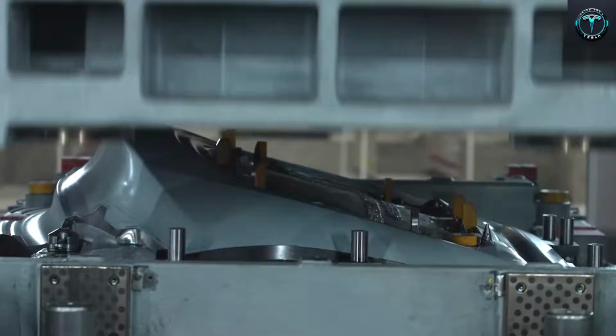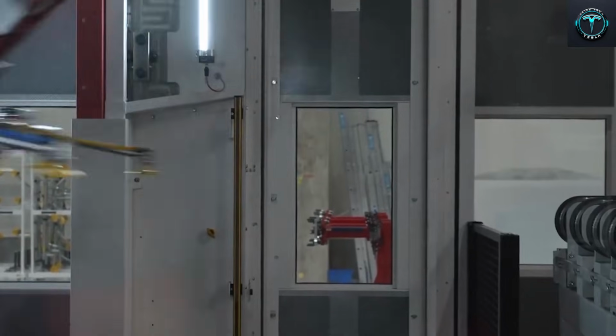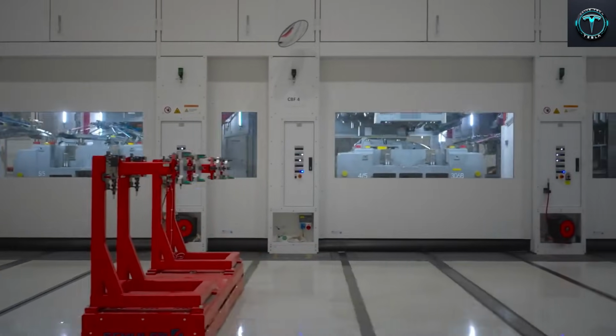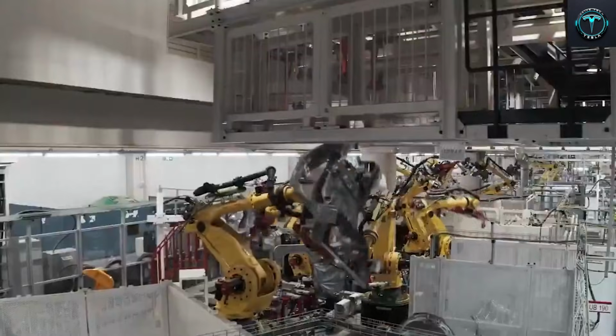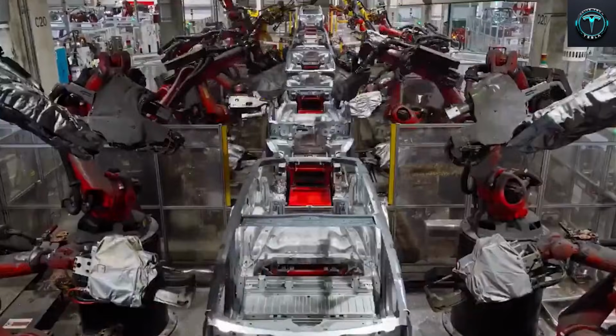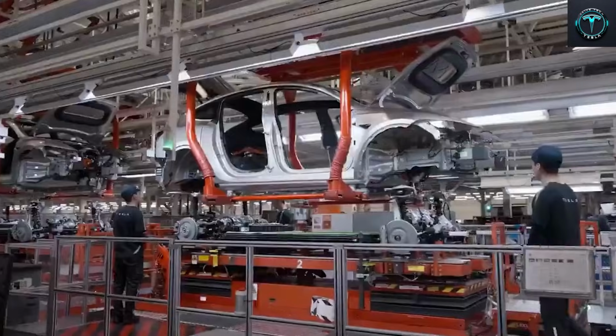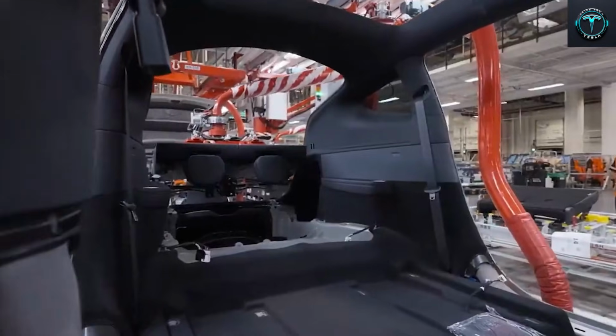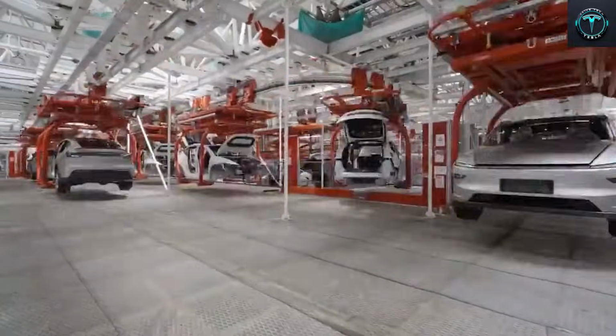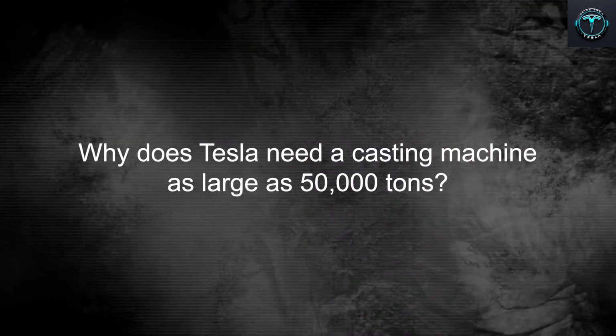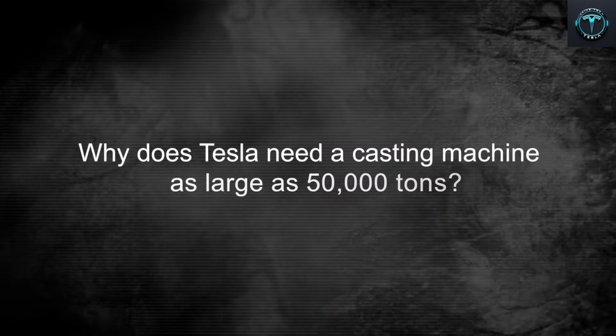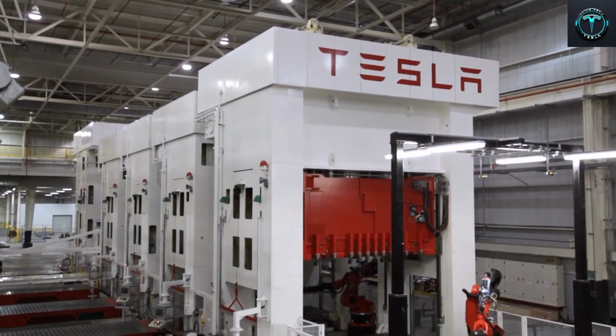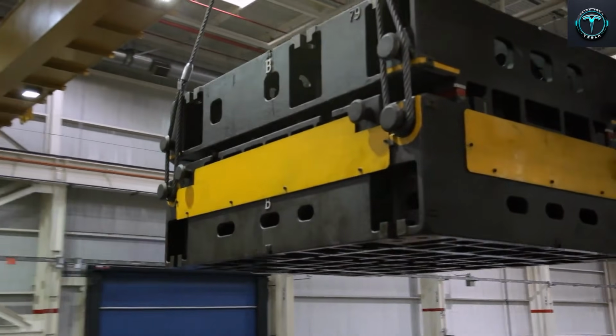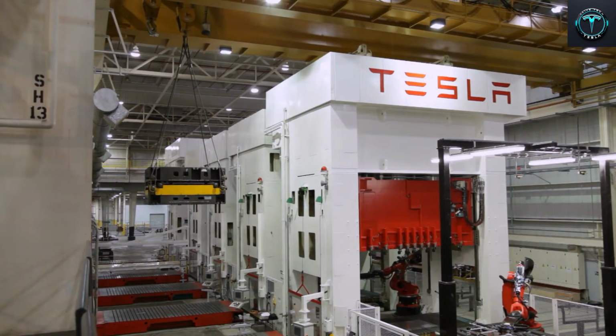The 50,000-ton Giga Press is the key technology enabling the Model 2's price and scale by creating a major leap in automotive manufacturing compared to traditional stamping. Stamping requires dozens of steps for a conventional underbody, 300-plus steel components, 3,000 to 4,000 welds, which accumulates errors, increases costs, and extends chassis manufacturing time to 20 to 30 hours per frame, also leading to noise and vibration. Giga Casting eliminates these issues. It cut the Model Y's rear underbody from 70 parts to 1, reducing cost by up to 40% and weight by 10%. With the 50,000-ton generation, Tesla cast the entire Model 2 underbody in a single shot, an unprecedented achievement.